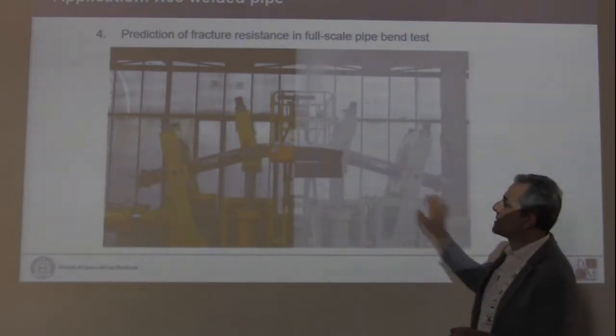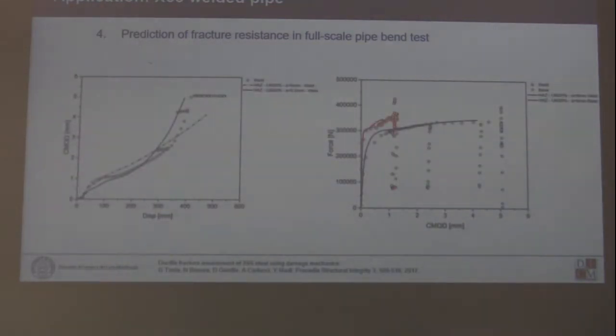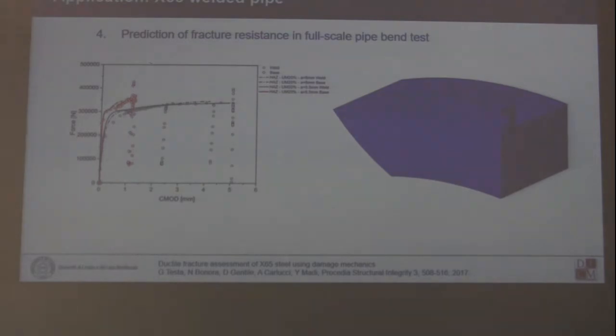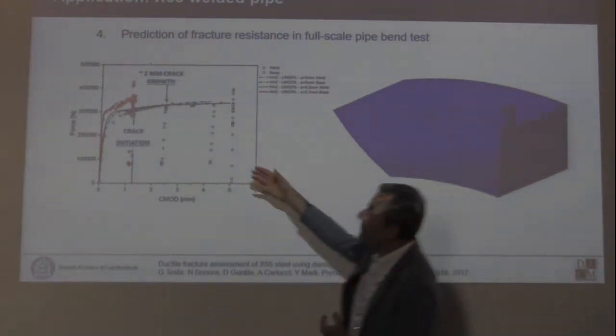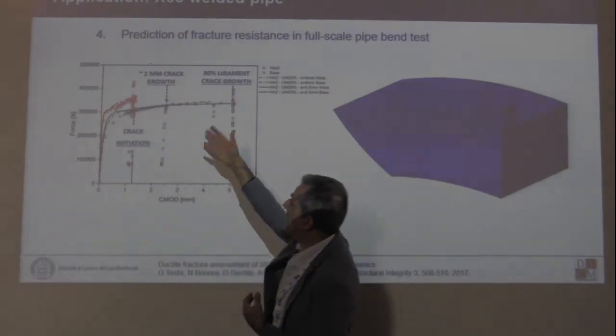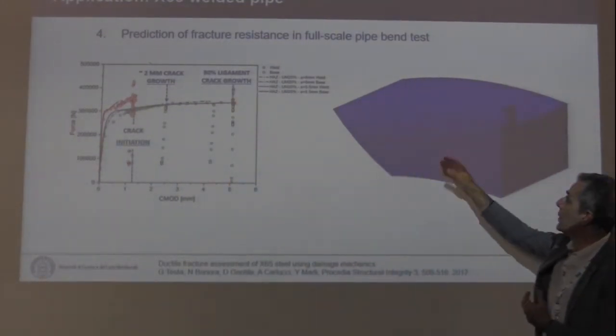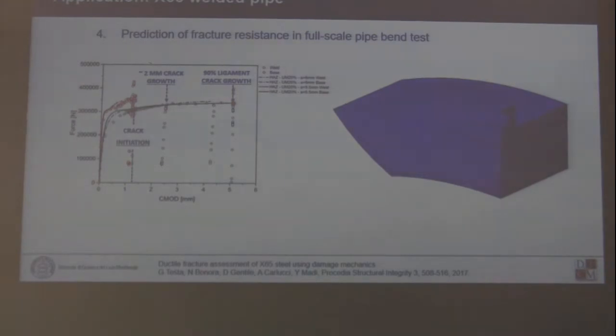And when we move to a full-scale test, as in this case, this was a full-scale test in Germany that was monitored, we were able to predict the overall response, the time from crack initiation, the extension of the ductile crack growth, and all the features that the pipe was showing in a full-scale test.